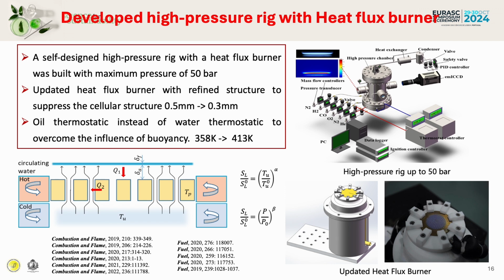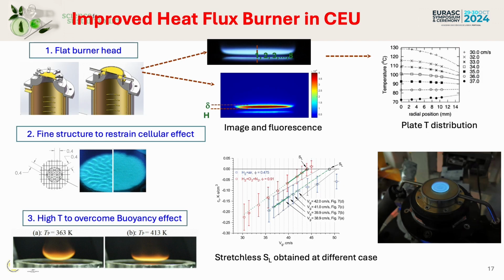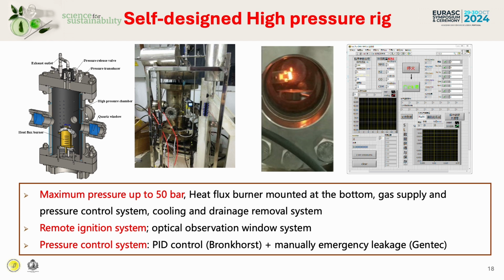What we have done is update the typical design of the heat flux burner. The original design has 0.5 mm holes drilled in the brass. We updated it with 0.3 mm holes inserted with 2 thermocouples. We updated the burner head design with a flat structure, easy for image taking. Secondly, we use a fine structure to restrain instability. The third is that we use a higher-temperature oil thermostat to overcome the buoyancy effect. At the same time, we designed and made a high-pressure rig. We put the heat flux burner into the high-pressure rig. The rig can hold up to 50 bar, with pressure control, cooling, and ignition, with software designed by ourselves.